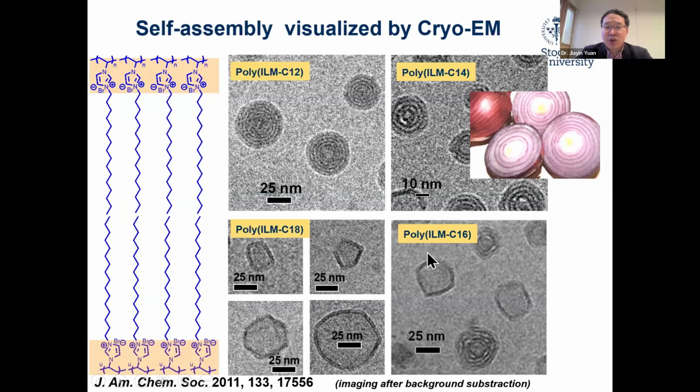And when the alkyl chain length goes further, you end up with unilamellar vesicular structures. And what is very unique, you can see the facet-like morphology, right? It is not spheric as you might expect. The laminar morphology is expected because the hydrophilic backbone, the imidazolium bromide, does not like the long alkyl chain. So the long alkyl chains naturally pack together to form the lamellar morphology.